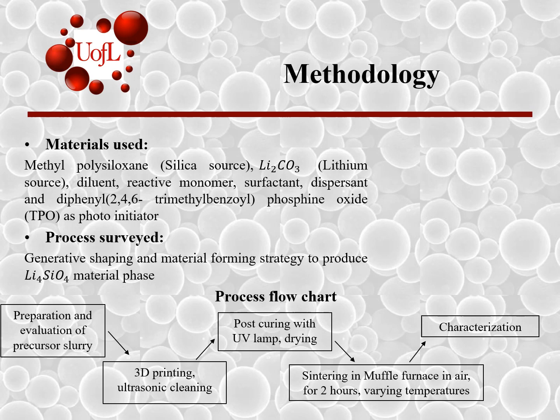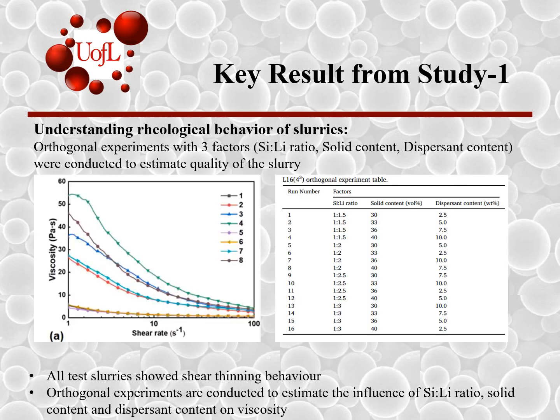They are then sintered in a muffle furnace in air for 2 hours at 4 different temperatures to study the effect of sintering temperature on the mechanical properties. Key result 1. In order to completely understand the quality of the slurry, orthogonal experiments were done. In these, all the independent factors that can affect the output parameters are grouped, making a set of experiments. This reduces the number of experiment runs and gives a clear understanding of the trends of different variables at play.